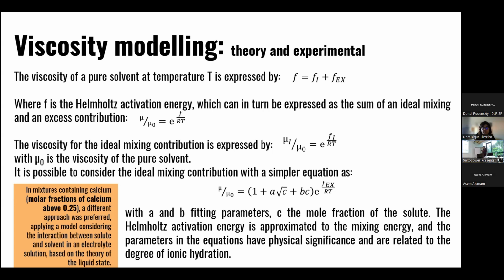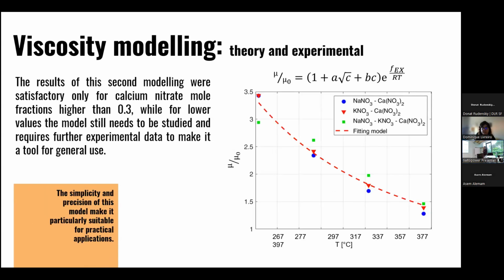And we decided that it could be a good approach also because these parameters in the equation have a physical significance and are related to the degree of ionic hydration. So I show you the results for this mixture containing calcium, and the results are more accurate than before. We stated that they are satisfactory only for calcium nitrate fraction higher than 0.3, and we are still investigating in more detail what happened with the calcium.